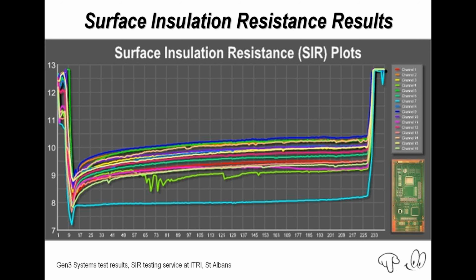and on the next slide, this graph actually shows you the results that you might get after processing a special test coupon. And you're looking at the insulation resistance over time, and what you're seeing here perhaps is that the blue line illustrates a failure. We've subjected the board assemblies to a hostile environment, and we've seen a drop in the insulation resistance, and it's not recovered at all.